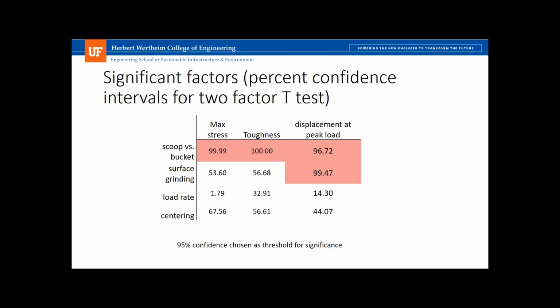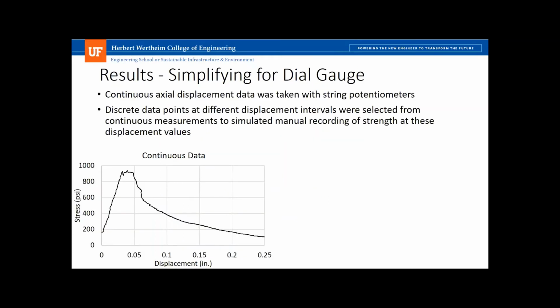The load rate didn't matter, even that big of a load rate. You know, we see a lot of talk about how the displacement rate needs to be controlled precisely. We found it was not statistically significant in this test, and that's because of the ductility of the sample. A lot of those issues matter less when you have a ductile sample. You're not getting impact loads, and that elastic release isn't affecting as much. And the centering was not statistically significant either. Centering is actually pretty easy to control. You can use templates to help you get it centered right.